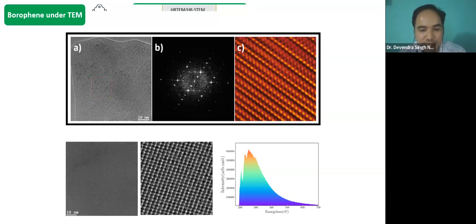So at the atomic scale, we can see those structures, we can see those two different phases. And of course, from the spectroscopy, which is electron energy loss spectroscopy here, we can verify that this is the pure phase, because every element has its own characteristic signal, which gives you the idea of what its coordination number is, what its structure is. Therefore, with the spectroscopy, we have verified that this is a pure Borophene phase. Next.